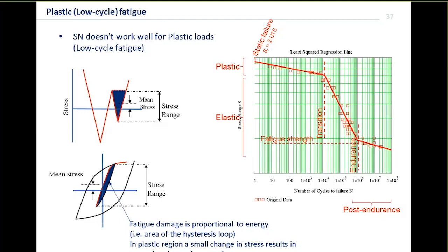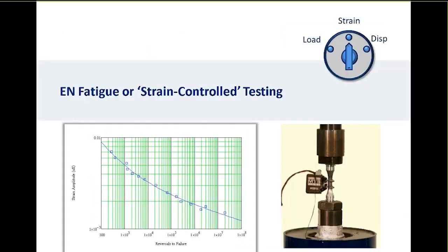So typically we only use SN up to the elastic limit, and beyond that we need to use strain, because strain is much better related to the component that's really doing the damage, which is strain energy. That really is where EN, or strain-controlled testing, came in. It allows us to consider those low cycle fatigue, high amplitude cycles, which may only occur once in a blue moon, but they do create exponentially more damage.